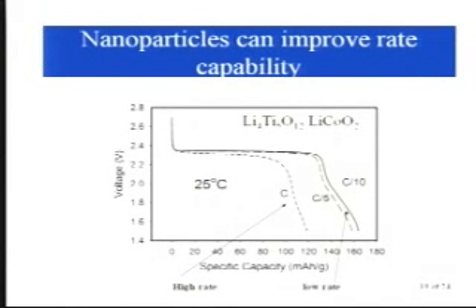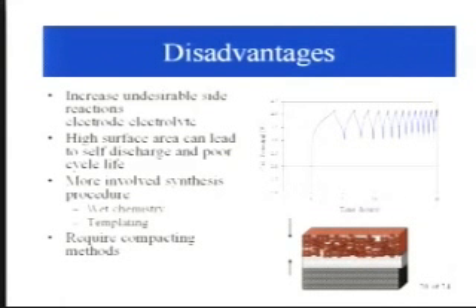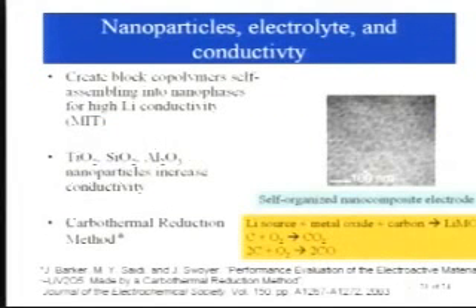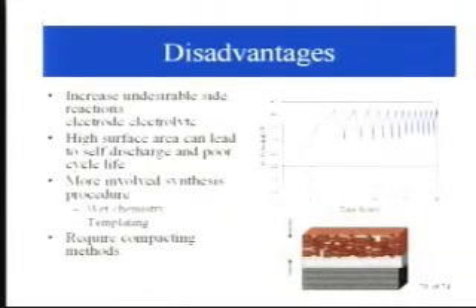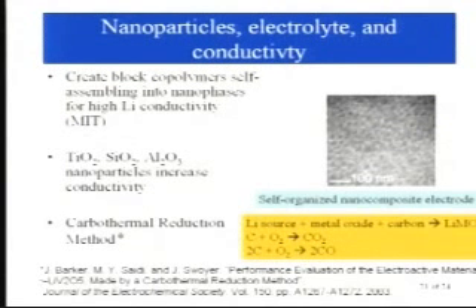So again, you can see the specific energy is the area under the curve, the voltage versus specific capacity, and it tends to be lower with higher rates. But some disadvantages are there can be undesirable side reactions. This is an example of a bad cycle profile. Then there are some examples of use of nanoparticles, and not necessarily in the cathode material, but TiO2 and silica, for example, have been used as very small particles to increase conductivity.